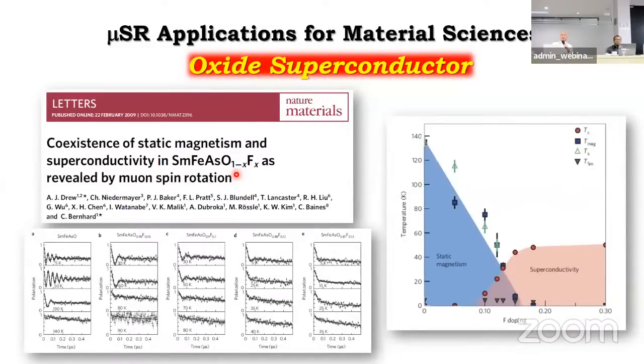So this one is related to this study, the iron superconductor, how the magnetic phases are merging with the superconducting phase. This kind of phase diagram study is very easy for MuSR. As long as we have samples, we apply the muon to the sample, and we can measure the magnetic state and also superconducting state within a very short time. If you do the similar measurement by using NMR, ESR, neutron, it takes longer time. Instead, for instance, this data was obtained within 3 days. Then we got the Nature-series material, Nature-series data. So that means the muon showed a very quick result, especially for magnetic materials or superconducting materials. That data is quite fast in the world.